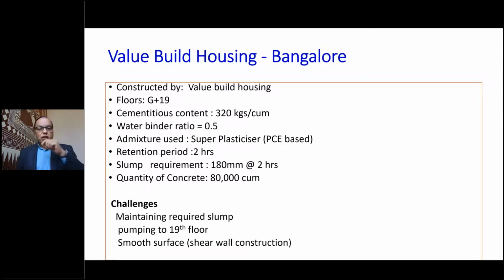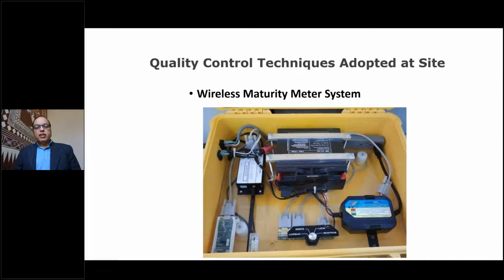But then look at the quantity of concrete that was required for the project, 80,000 cubic meters, and that so much of quantity should have as consistent strength as well as consistent slump. Therefore, the challenge there was to maintain the required slump and pumping it to such a great height. And it was a shear wall construction. Now, in this, instrumentation was used in the concrete.